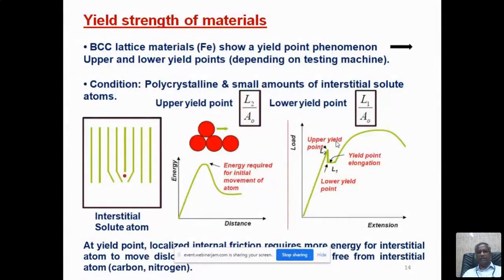The condition for this yield point phenomenon is that it normally occurs in polycrystalline materials which have interstitial solutes. There are 5 interstitial elements: carbon, nitrogen, boron, hydrogen and oxygen. These are the 5 interstitial elements that can be added into the material. If you take iron and add carbon, it becomes steel. Similarly you can add boron to iron, or remove some carbon and add nitrogen, which also acts as an interstitial element.